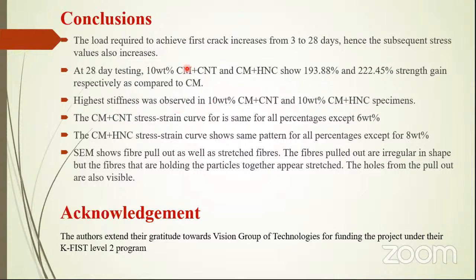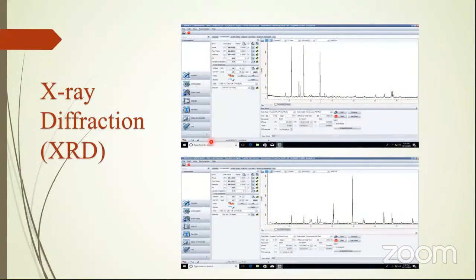And highest stiffness was also observed in similar specimens. And as I said, the CNT stress curve is the same for all percentages except for 1, which is 6, and CM and HNC is also the same for all percentages except for 8. And SEM shows fiber pullout as well as stretched fibers, which I explained.